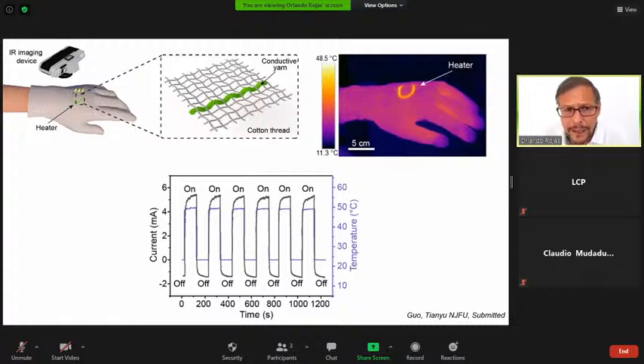Another example is that, being a conductive material and having some degree of resistance, we can also integrate those filaments in wearables, in wovens or non-wovens. And in that case, by applying a current, we can produce Joule heating. What it means is that we can locally produce heating by applying a current. That response is shown in the bottom, as we see how with the current you can change the temperature of the material quite nicely. So for local heating, it's an application that shows the electroactive properties of this type of filament.